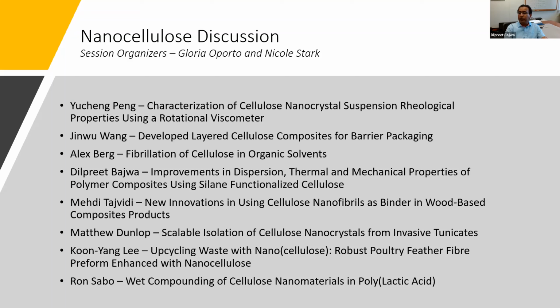The next thing, we also noticed that there was an increase in the thermal stability with the increase in silane amount in the system. The increase in the thermal stability was attributed to the polysiloxane network grafted onto the surface of the CNCs. And similarly, the highest crystallinity was observed in the samples with 1% silane treatment. And that crystallinity was around 55.14%.